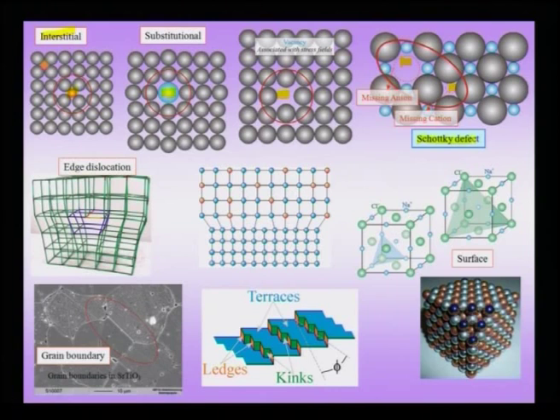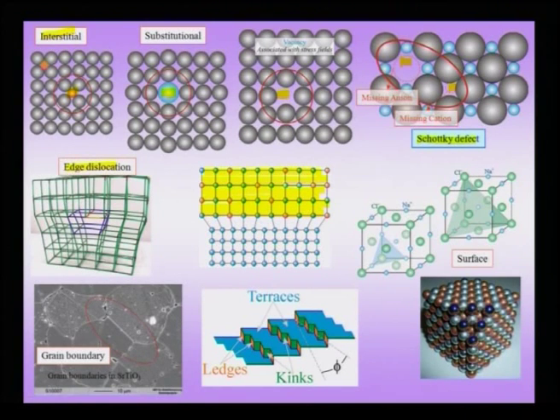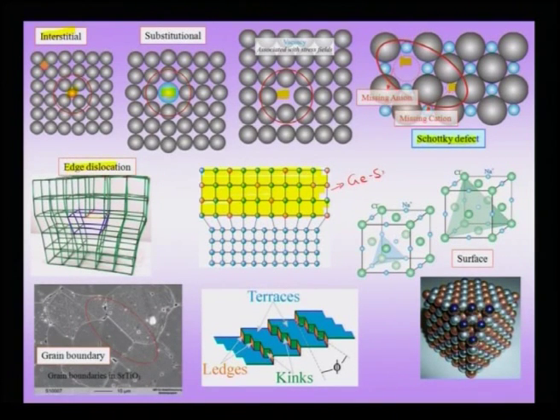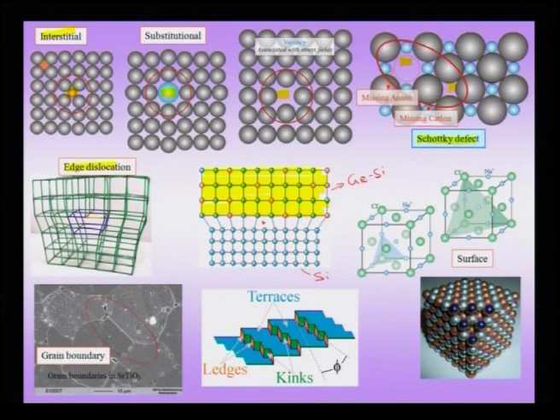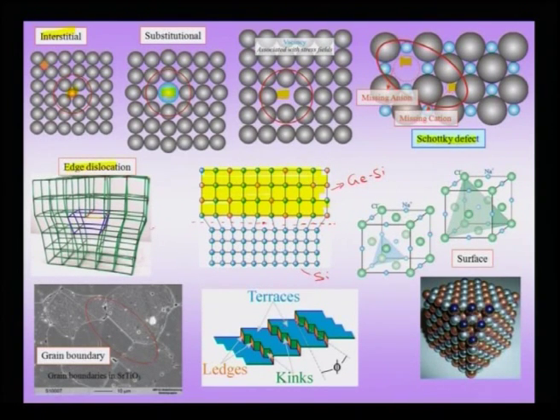We have seen the example of an edge dislocation, which can also be present at an interface between two materials — for example, germanium-silicon solid solution on one side and pure silicon on the other. The dislocation present at the interface is an interfacial misfit dislocation and, in some sense, belongs to the class of structural defects localized to that interface between GeSi and Si, unlike the random dislocation shown in the other diagram.